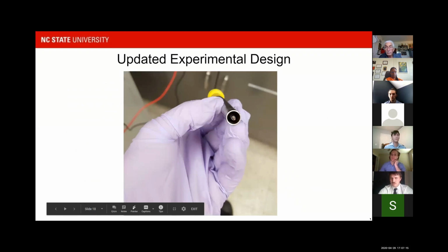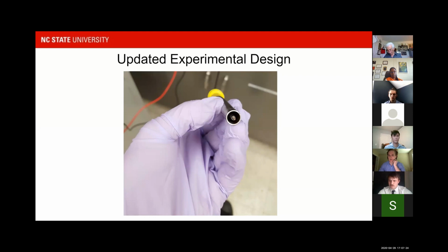Here you can see the bottom portion of the zirconium cladding that was submerged in the chromic acid solution. The material that we went with for the anode was stainless steel. Now, stainless steel can be used as a plating anode, though it's recommended that a lead tin alloy or platinized titanium be used. But to get pure lead wire of a certain diameter is difficult to find, and we were operating under some time constraints, and oftentimes to get either a lead tin alloy of a specific composition or a pure lead wire of a certain diameter, you have to special order that, and there are lead times. But Ryan suggested we go see Irvin in his office downstairs of Burlington, and he was able to supply us with a stainless steel anode, and that's what you see here.